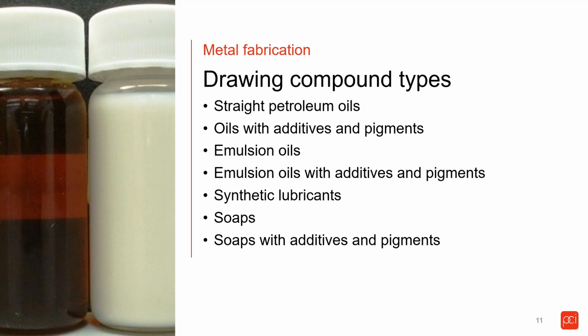Another very popular drawing compound is an emulsion. An emulsion is a straight oil with a compound in it called an emulsifier, which allows it to be mixed with water. So you can actually dilute the oil using water, and it will mix together as one solution. If you look at the picture on the left of the slide here, that's a side-by-side picture of a straight oil on the left and an emulsion on the right. The emulsion kind of looks like milk. And again, with the additives and pigments, that's where you can run into issues with cleaning.